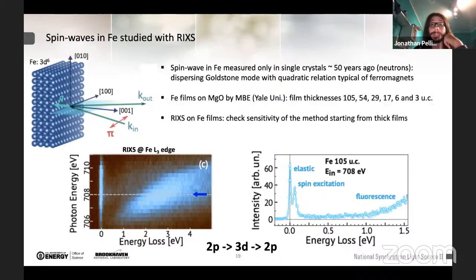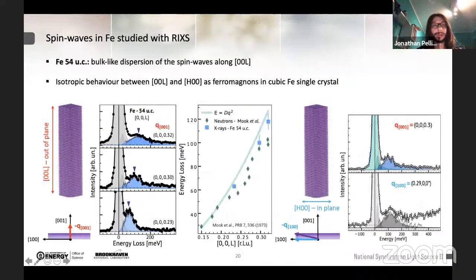So here I'm showing on the left-hand side of this slide the momentum dependence of our RIXS spectra for an bulk-like iron film. Essentially what we observe is that as we decrease the transfer momentum to the system, the peak that we ascribe to the spin excitation is decreasing in energy and dispersing. By performing this measurement, we were able to collect the spin excitation dispersion for an iron film as a function of momentum along the 0,0,L direction.